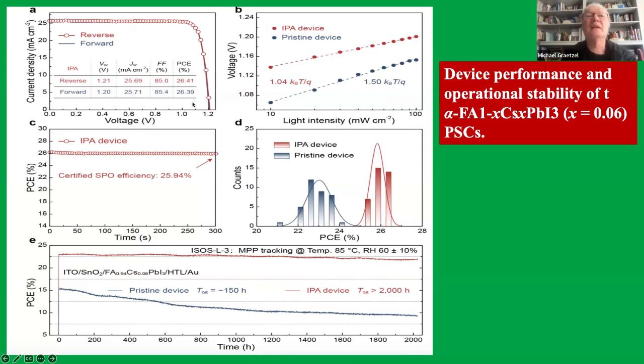And then you can see the stability. That's really now becoming the most important parameter. Can you show long-term stability? Of course, we cannot wait 25 years to see how well the perovskite solar cells do outdoors. Although outdoor tests are ongoing, they are slow. So how do you get an answer whether your formulation in your cell is stable or not? You have to do accelerated tests. One of the most challenging tests is to have the combined stress: high temperature, high humidity, and maximum power point tracking. Maximum power point tracking means that you keep the cell at the maximum power point of the voltage.